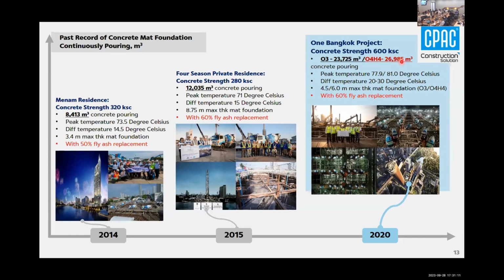The last one that I would like to talk about today is the mat foundation of the One Bangkok project. This one is very special because the specified strength is C60 MPa. You can imagine that very high strength, and the thickness is around 6 meters. So when I heard that this project was going to start, we were quite worried about the concrete, because the owner and the contractor would like to cast the concrete in one time. Otherwise you need a lot of days to cast the concrete, you need a lot of rebar, and you need a lot of shear keys to transfer when split casting. You have a lot of work to do. So within one time, we already did that, but I will give you information later on.